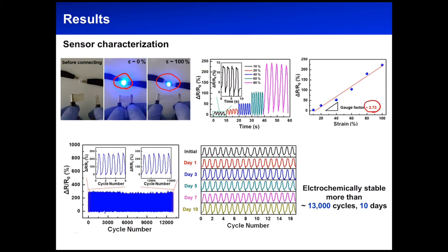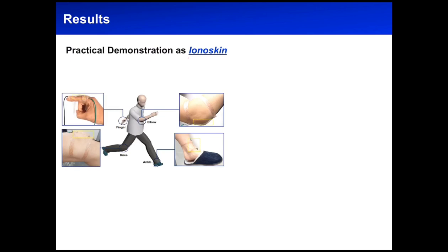The gauge factor, the ratio of the resistance variation to the applied strain, is 2.73, which is a relatively high value compared with previous strain sensors. We also demonstrated the stability of the gel. The ion gel strain sensor well maintained the initial amplitude of resistance change even after 13,000 stretching and releasing cycles, and was stable for more than 10 days without any encapsulation process, due to the highly non-volatile properties of the gel.